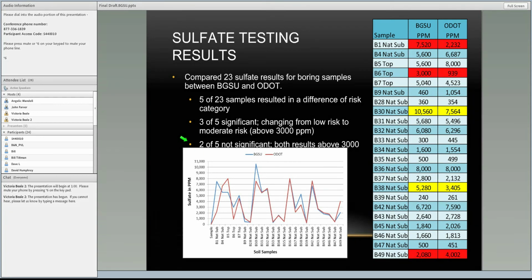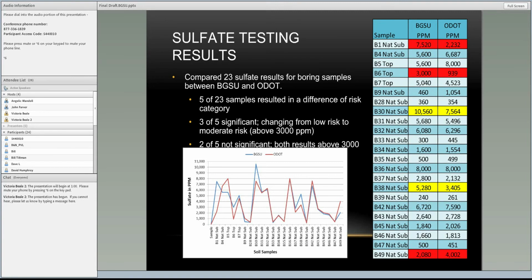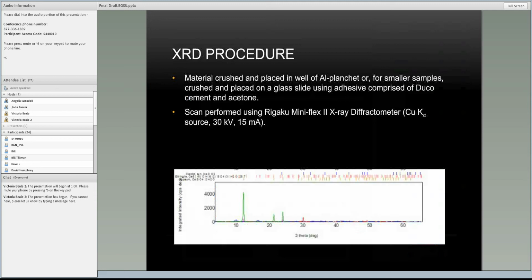And the graph at the bottom is just a visual comparison of our results. And you can see that we did a really good job, the 2 different labs, of following each other. And also that a lot of the results were above 3,000 parts per million in sulfate. We also, with these boring samples, took the same soil that was used to run the sulfate test. We actually ran an XRD on it first before we used that soil for the sulfate testing. So the XRD results corresponded with the sulfate of the same boring.